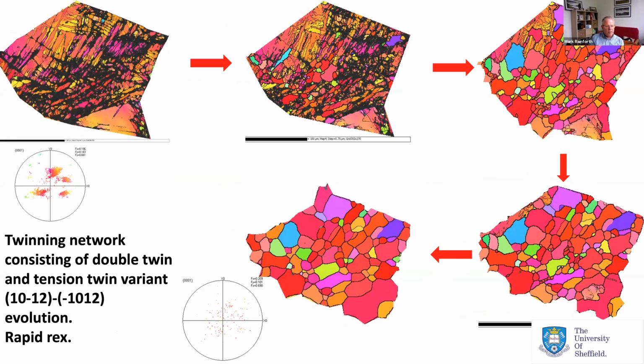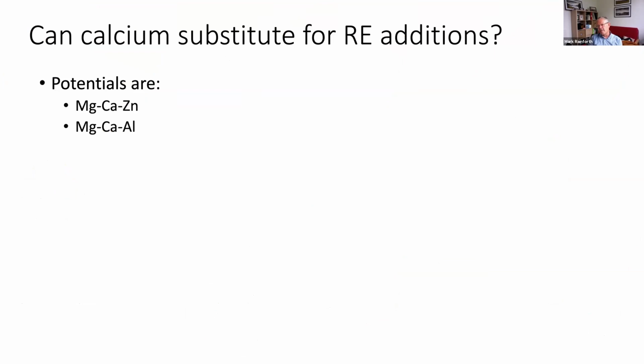On the other hand, in double twin variants, it's quite different. Then recrystallization occurs within the twins. And as these grow, they tend to give this distributed texture, which is what we want. In other words, not a strong texture. So the question here is, are there other additions that we can put in that would do the same as the rare earth additions? Now, there's been a lot of interest, and COSCO have led on this in producing magnesium, calcium, zinc alloys, where calcium seems to behave very much in the way that the rare earth elements do.